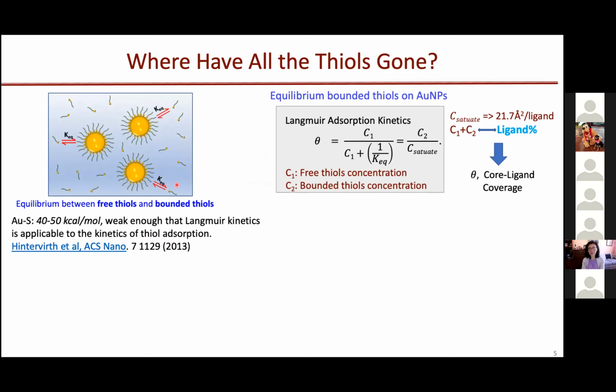This was backed by experimental measurements using various techniques to determine the equilibrium constant. Using the Langmuir absorption equation and the equilibrium constant, we're able to build a relationship between the equilibrium bonded thiols on the gold nanoparticle, theta—which we call core ligand coverage—and the free thiol concentration.